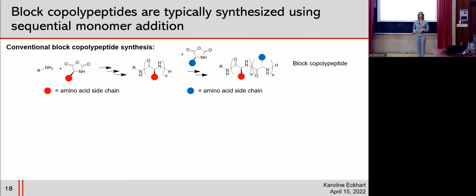So typically when you're making a peptide amphiphile or block copolypeptide, and this is actually the way that I made the keys, we use sequential monomer addition. With this strategy, you first polymerize an NCA with a certain amino acid side chain, and you form the polypeptide. And then you add in a second type of NCA with a different amino acid side chain, and this gives you a block copolypeptide.